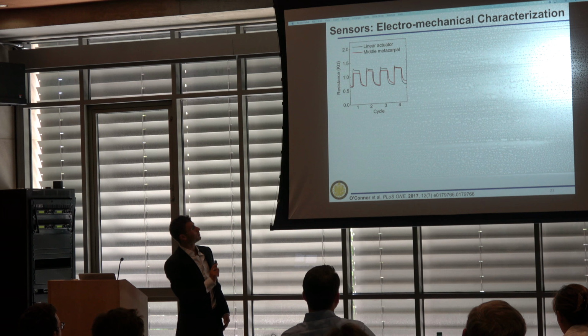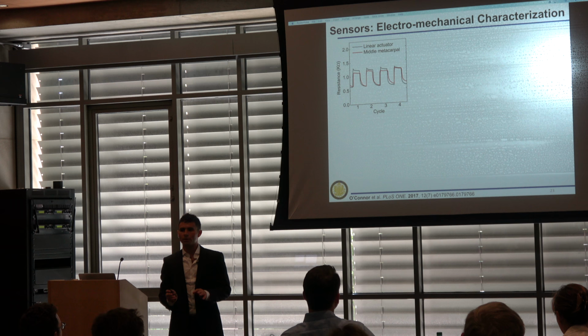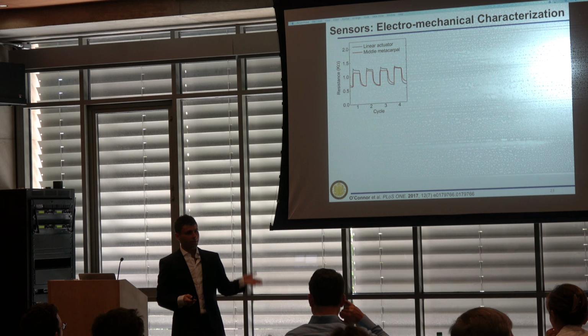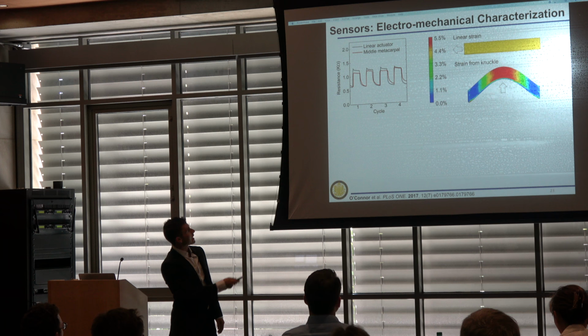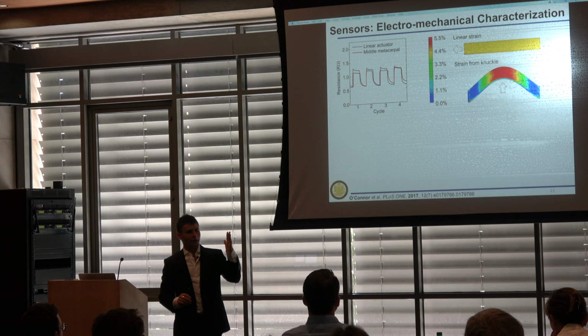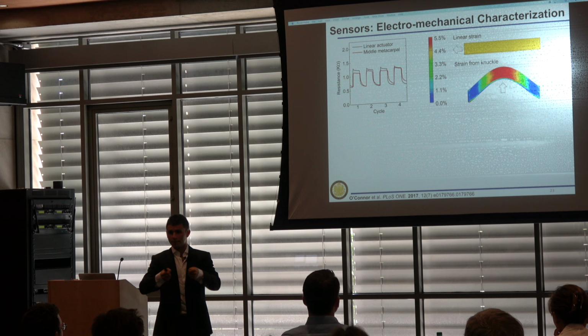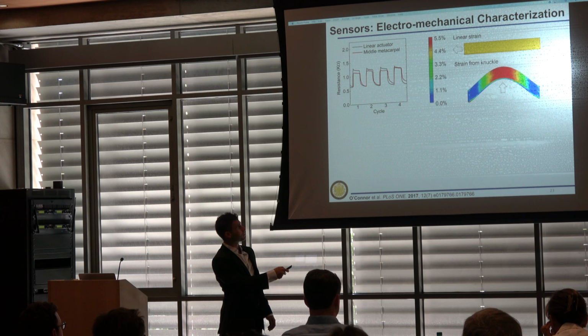In order to estimate the strain being applied to the sensors, we put these sensors on a linear actuator and did a controlled stretch. We approximated the resistance increase, and we got about 4.4% strain. But this is in a linear strain mode. When you put the sensor on the back of a knuckle and flex your hand, the strain will not be evenly distributed as it would if you grabbed it by both sides and pulled it linearly. So we have this uneven strain distribution, and we used finite element analysis to model the strain distribution.